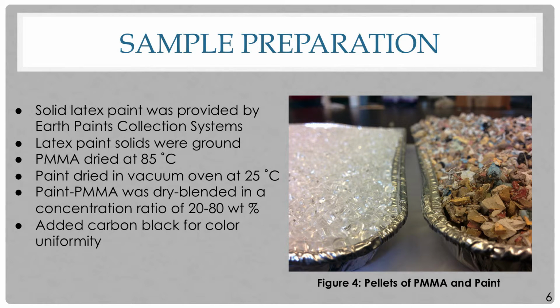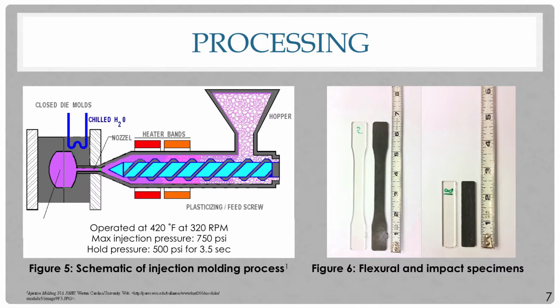We began our research by preparing the latex paint and the PMMA for injection molding. The latex paint was first collected from Earth paint collection systems and then was ground into flakes. The latex paint was then put into a vacuum oven at 25 degrees Celsius for 24 hours. The PMMA, on the other hand, was already in the form of granules, and it was placed in a mechanical oven at 85 degrees Celsius and was run for 24 hours to remove any water molecules that may have been absorbed. The injection molding process is used to mass produce plastics of various sizes, shapes, molds, and designs.